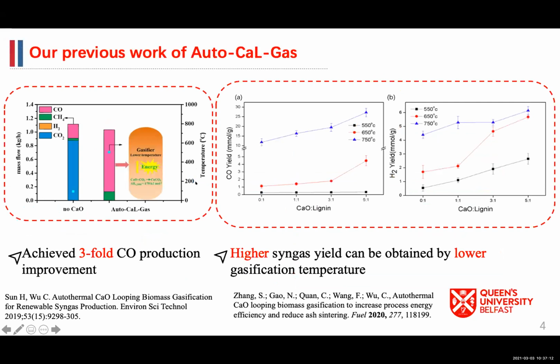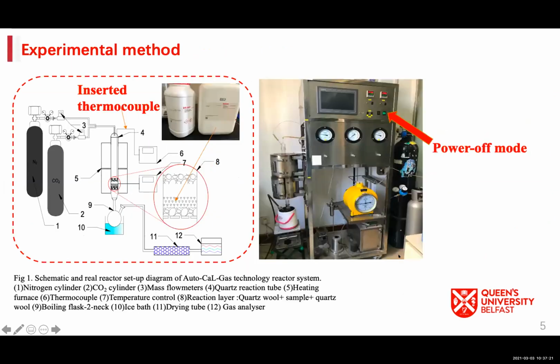So a little bit of our previous work, we achieved threefold CO production improvement, and higher syngas yield can be obtained by lower gasification temperature. So in this case, we use the power off mode, which means that because reactor power always has an influence on the temperature of gasification, we use the power off mode. After reaching the set temperature, for example 650 degrees, we shut down the reactor power to see the possibility of calcium oxide carbonation supplying the gasification process. And in order to observe this phenomenon, we insert a thermocouple to observe the temperature difference.